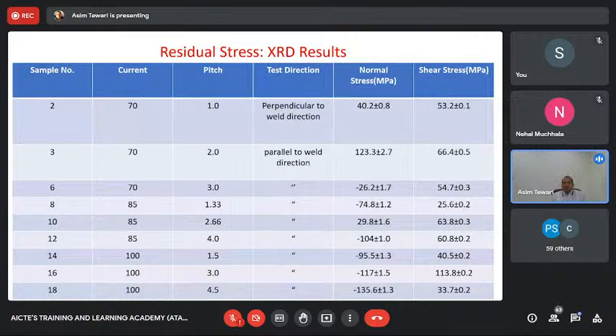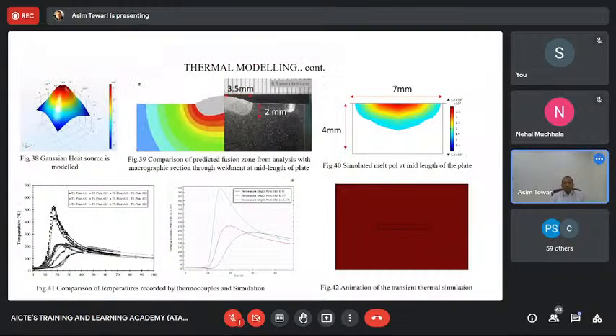So then coming to, once we have this, what does this tell us and how can we now model this? And that is where the main challenge comes. So essentially we need to perform a modeling, and I'm just showing you one aspect, and then I'll get into a slightly more detailed aspect of understanding and exactly predicting these. So what you're seeing is that as you are heating and you have a heat source which is moving, the heat source is never a flat heat source. You have more heat at the center and less heat at the sides.